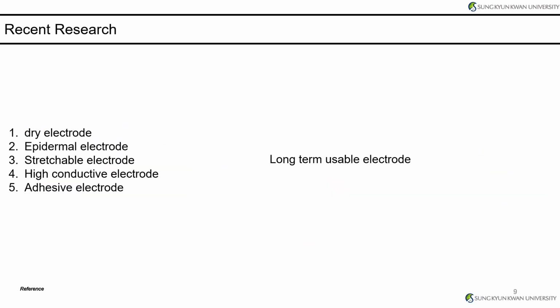The fulfillment of the five conditions mentioned earlier, a dry electrode, epidermal electrode, stretchable electrode, highly conductive electrode, and adhesive electrode, can be confirmed through long-term skin-electrode impedance measurement. If any of the conditions are unsatisfactory, impedance increases, leading to a decrease in signal quality. However, various dopants have different trade-offs, so it is difficult to meet all five conditions mentioned above. The aforementioned papers also lack data for long-term measurement due to unsatisfactory fulfillment of one or two of these five conditions.